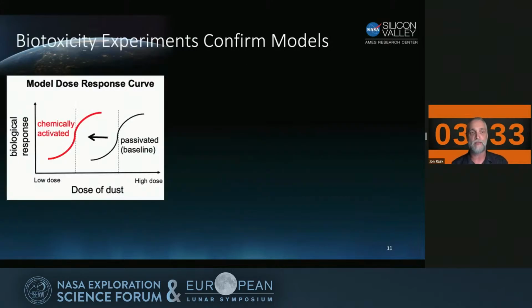the lunar environment. And to drive this home, we've done some biological studies in rats. Biological response is going to increase as a function of dose, and the dark line on the right is considered a passivated or low reactivity sample. And if we chemically activate lunar material, it will shift the biological dose response curve to the left in what we would call a chemically activated dose response curve.